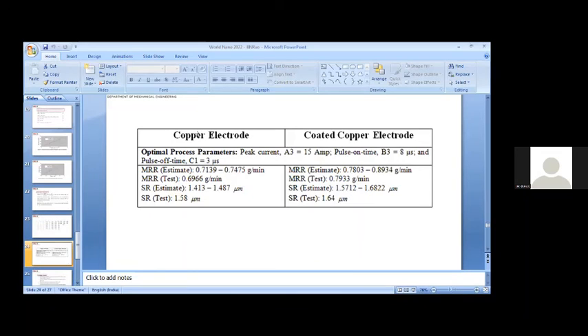So when you see the copper electrode and the coated copper electrode, the optimal process parameters are peak current 15 amperes, pulse on time 8 microseconds, and pulse off time 3 microseconds. The MRR estimate is this range, whereas the test result is this. The surface roughness estimation is this, whereas the test result is this. So when you go for the coated, from the factors arrived, we are able to get 0.78 to 0.89 grams per minute, whereas the test result is 0.79, that is in between. SR estimate is 1.57 to 1.68, and the test data is 1.64. So these are all falling within this range. This confirms the validity of multi-objective optimization.